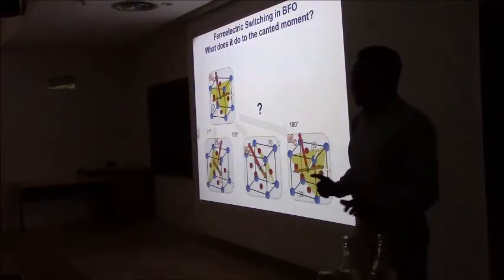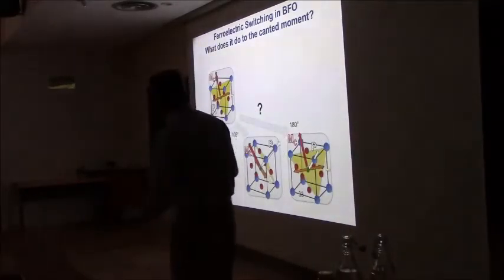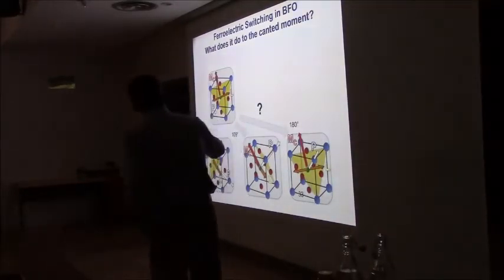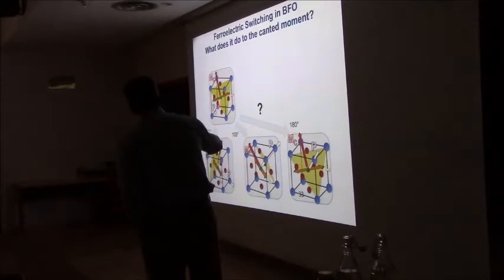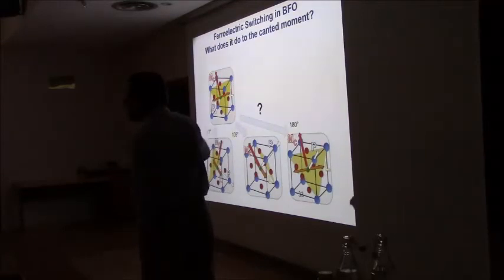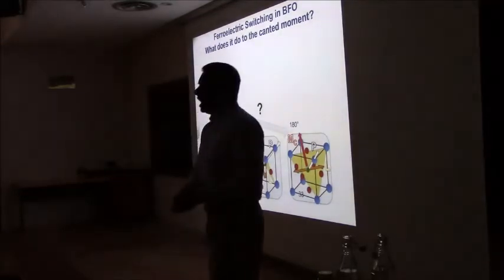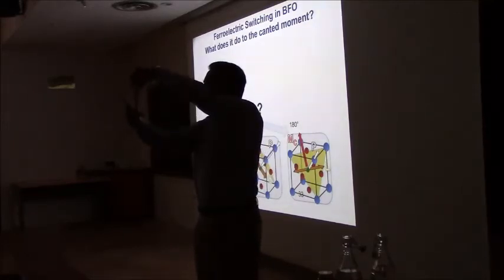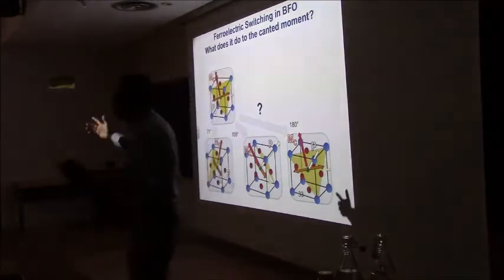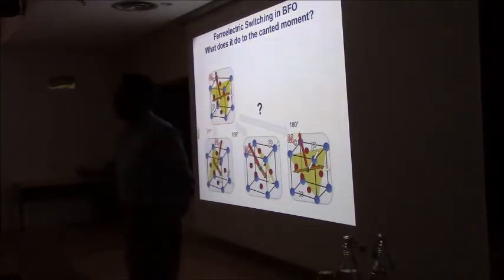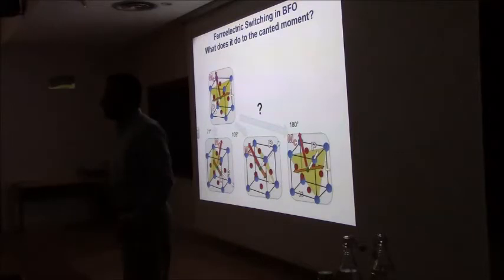Okay. So the first question we're going to ask is, if I switch my ferroelectric polarization, what happens? This is a little bit complicated picture, but let me take you through it. The white arrow is the polarization. The red arrow is the canted moment that we saw before. The orange is the antiferromagnetic L vector. They have to form this right-hand screw: P along 111, L and M. The L is typically in the 111 plane. Let's pick the 110 direction, or 11 bar 0 direction.